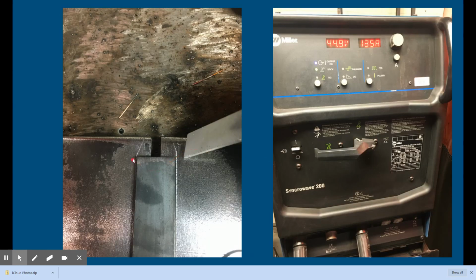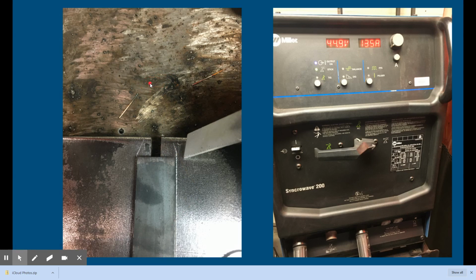Once I do that, I'll take the backing strip and mark it with soapstone so that it's centered on my groove. I'll slide it forward, mark the other side, and make sure I have enough hangout over here with my backing strip, and I'll put another clamp on top of that. Important, you do want to clamp that down as well, so you're going to get 3 clamps, and then I'll tack my backing strip on.